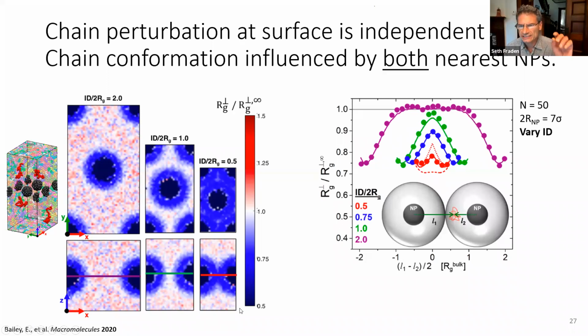Could you just clarify, is this RG calculated from an individual polymer, or is it monomer to monomer, and how are you calculating RG? So this is the radius of gyration of an entire polymer chain. These polymers are only 50 beads long. And what I forgot to mention was where do we put them on this distance between the 2 particles? That we do from the center of mass of the chain. So you look at a chain, you calculate its center of mass, you get its RG relative to the surface.